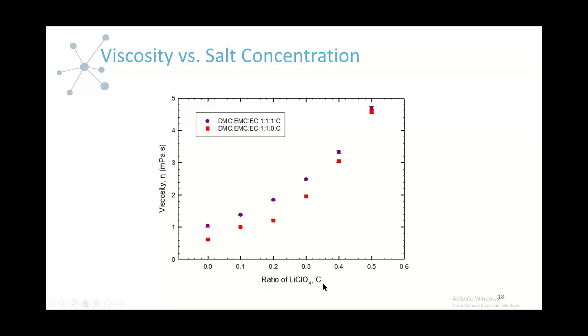This figure also shows the effect of lithium perchlorate concentration on viscosity. As expected, increasing the concentration of lithium perchlorate results in higher viscosity. For the EC-free electrolytes, a higher concentration of lithium perchlorate can be beneficial because it can assist with ion dissociation and increases the conductivity of the system.